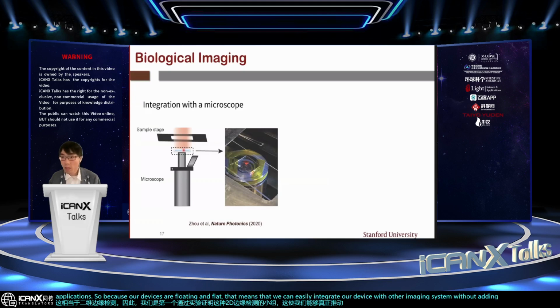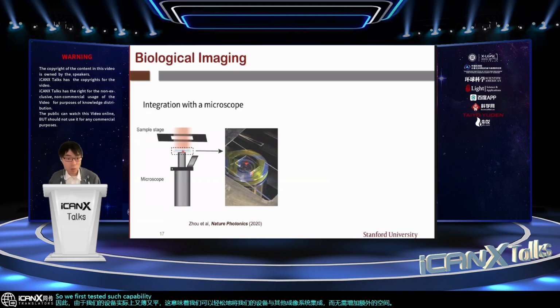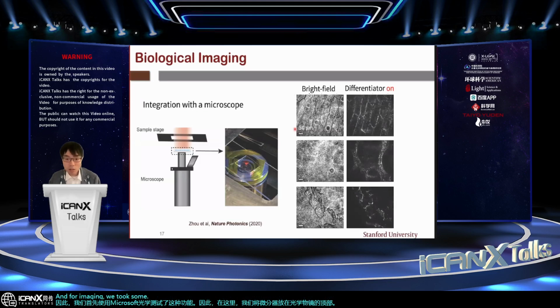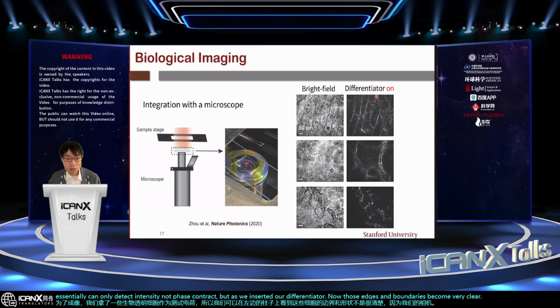So we first tested such capability with an optical microscope. Here we put our differentiator on top of the optical objective. And for imaging, we took some biological transparent cells as a test target. So we can see on the left column, those cell boundaries and shapes are not very clear because our camera essentially can only detect intensity, not phase contrast. But as we inserted our differentiator, now those edges and boundaries become very clear. So that means that with our tiny edge detector, we can convert a bright field microscope into a dark field.